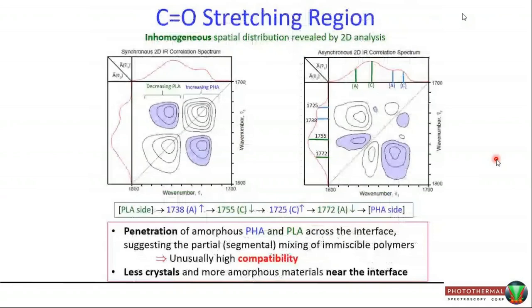Now what we see, in the carbonyl stretch region, moving from PLA side to PHA side across the interface, we observe two big autopeaks indicating the gradual decrease of PLA intensities, which is located at a higher wave number, and gradual increase of PHA signals, which is located on the lower side of the wave number. One is increasing and the other one is decreasing, so we actually observe this negative cross peak between PHA and PLA.